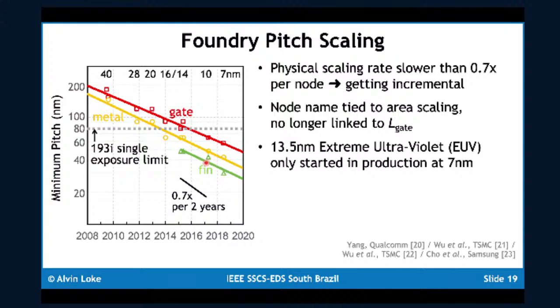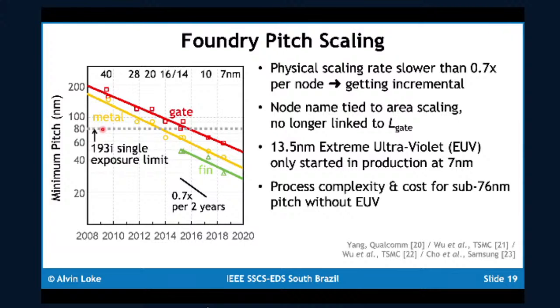So extreme ultraviolet did get introduced at 7 nanometers, but partway through 7 nanometers. In the meantime, with lithography limited to a single exposure limited to 76 nanometers for 193 nanometer immersion lithography, you can see a lot of points here beneath that threshold. So to achieve all these sub 76 nanometer pitch without extreme ultraviolet, first off, it's possible, but it comes with process complexity and cost.